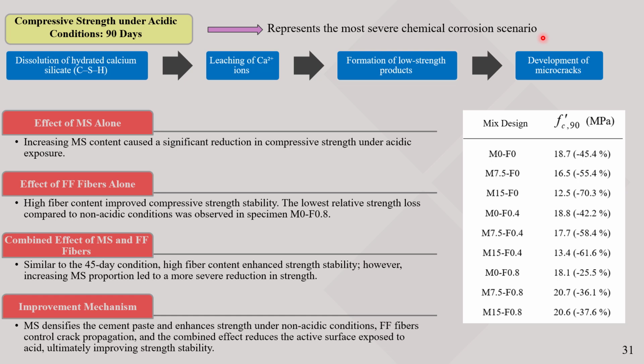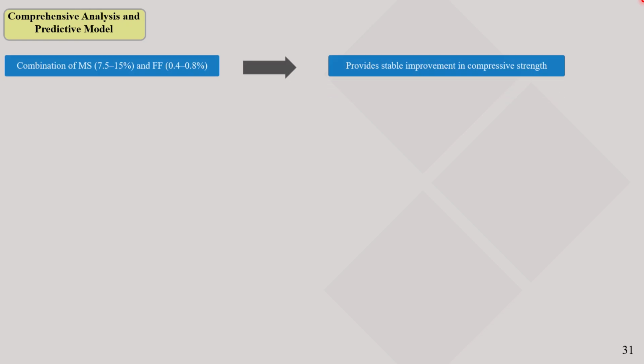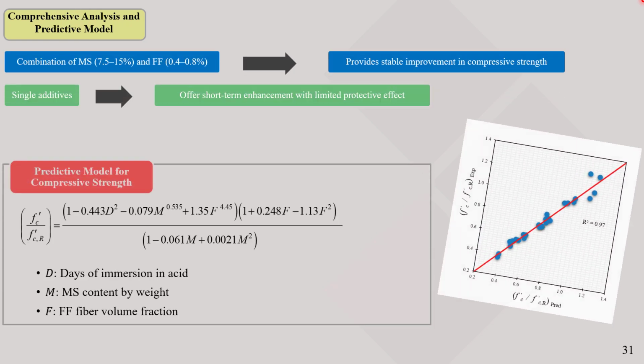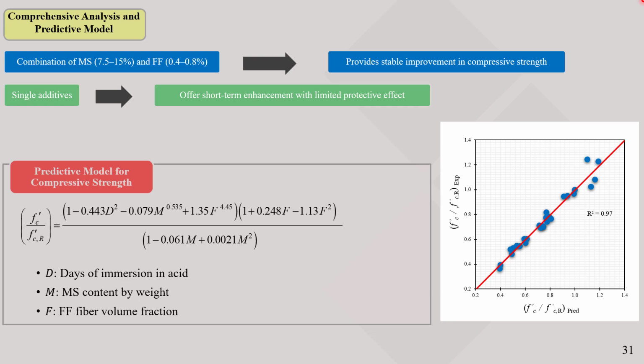The final conclusion was that combined samples with the highest fiber content performed the best. Microsilica can be used at 7.5% or even 15%, but the fiber content should be maximized. A comprehensive analysis of the samples was performed, and a predictive model was developed.